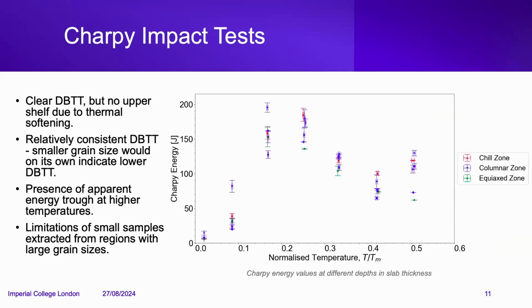So results-wise, as to be expected with ferritic or bainitic steel, you can see a clear brittle to ductile behavior happening here as you reach a peak, but you don't actually get an upper shelf due to the effect of thermal softening that happens quite soon afterwards.